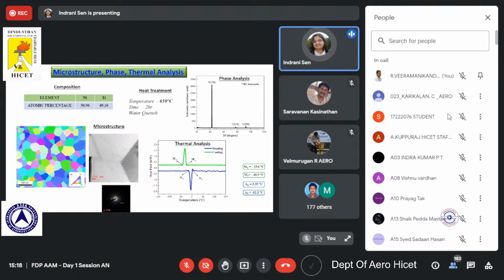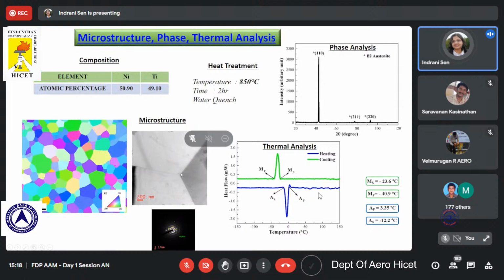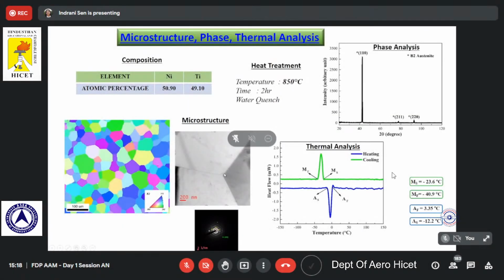Now, when we did the DSC, differential scanning calorimetry, we could figure out the martensite start and finish temperatures and the austenite start and finish temperatures. You can see that the martensite start temperature is minus 23 degrees centigrade. That means if we keep on cooling the alloy from 150 degrees centigrade, at minus 23 degrees centigrade it starts converting to martensite, and when we cool it to minus 150, it is fully martensite. Again, when we heat it, it starts converting to austenite at around minus 12 and finishes at around 3 degrees centigrade. So at room temperature, which means 30 degrees centigrade, this material is fully austenite.